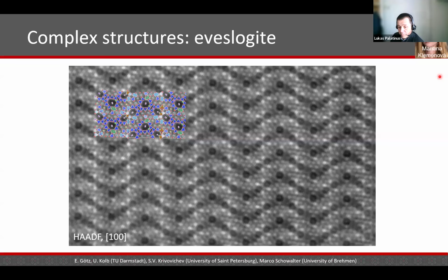And there have been many cases already reported where electron diffraction allowed finding polymorphs that were not visible by X-rays or powder X-ray diffraction, because they were minor, a small amount. But with electrons, you pick that crystal and you solve the structure even from a polymorph that is 2, 3, 4% of the total volume.